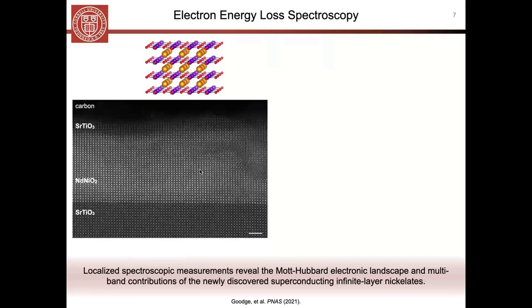And so these samples are only ever about 10 to 20 nanometers thick, and that's basically just related to the growth parameters that are able to stabilize the structure. And so what that means is that EELS and really detailed fine structure analysis of the EELS edges is uniquely poised to answer some really important questions about the electronic states in these materials, compared to some other bulk probes that have been used more traditionally, but that have a hard time avoiding contributions from things like the substrate or nanoscale inhomogeneities throughout the material.